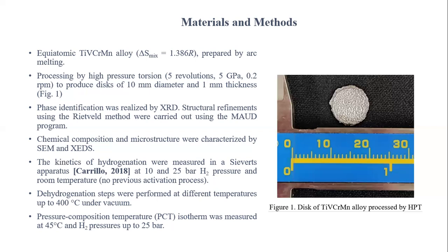The kinetics of hydrogenation were measured in a Sieverts apparatus. Hydrogenation at 10 and 25 bar hydrogen pressure at room temperature. No previous activation process was carried out. Dehydrogenation steps were performed at different temperatures up to 400 degrees Celsius under vacuum. Pressure composition temperature isotherms, PCT, were measured at 45 degrees Celsius and hydrogen pressures up to 25 bar.